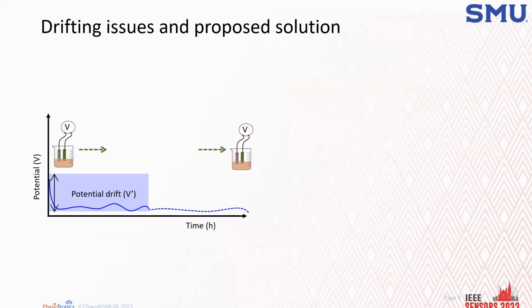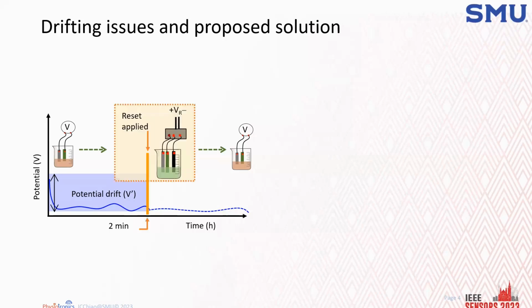What we are trying to do is this: if a pH sensor has a long drifting curve, usually what happens is that when you put the sensor into the solution, you have a spike, and then gradually the potential comes down. So when to measure the potential is very difficult to tell. What we want to do is convert it into something, and I will talk about that later, that makes the potential settle very quickly, so we know when to take the measurement result.